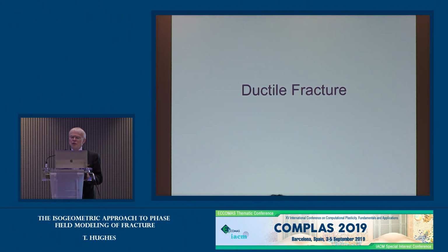In ductile fracture, one of the things you might want to do is to consider the peak stress as an ultimate stress or failure stress as a given, as well as the elastic properties and the fracture energy. If you do that for the different models, the cubic and the quadratic stress degradation functions, you get these different expressions here. If you equivalence them to get the same peak, then what you find is that the cubic model is giving you a much bigger L0 for the same peak stress.